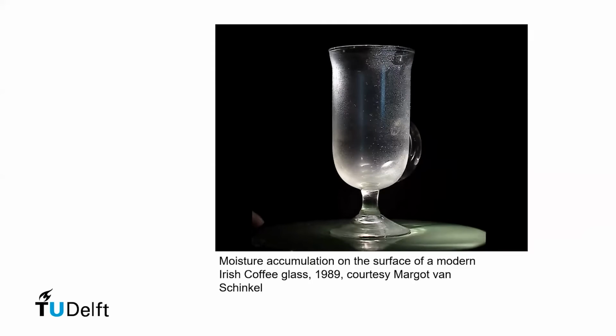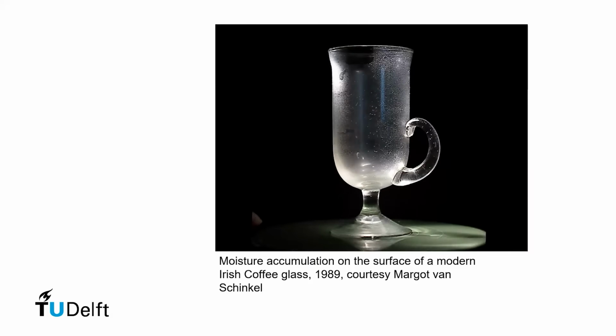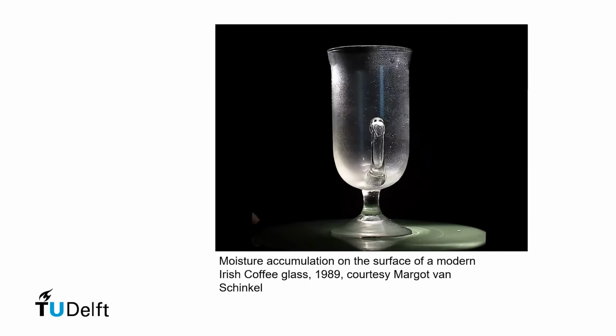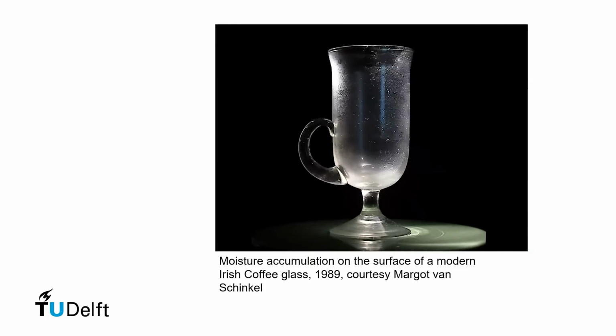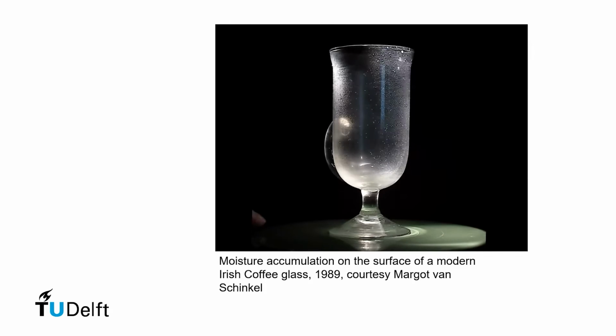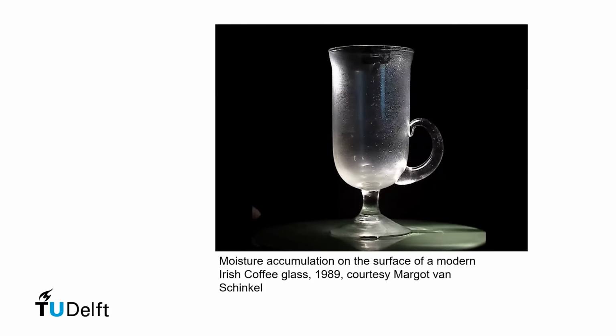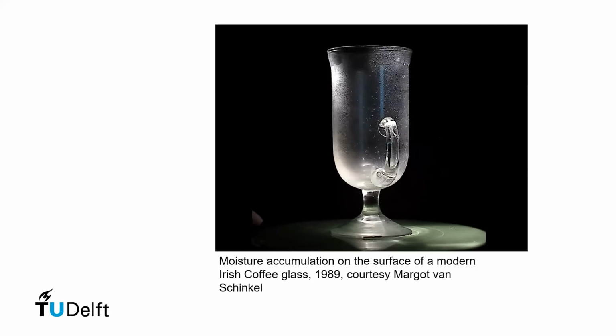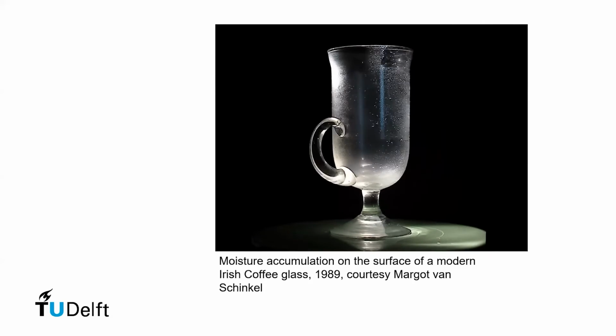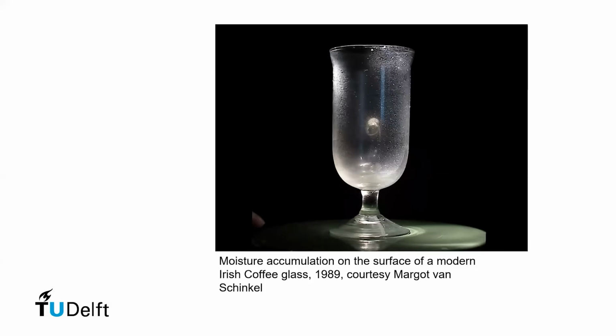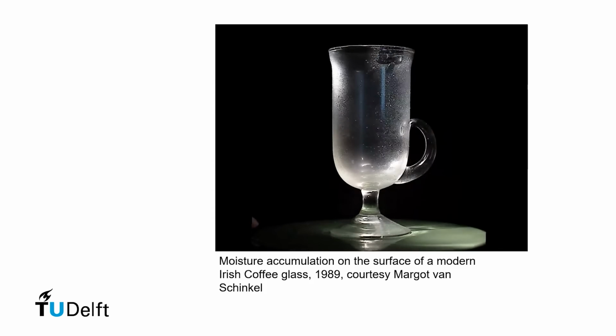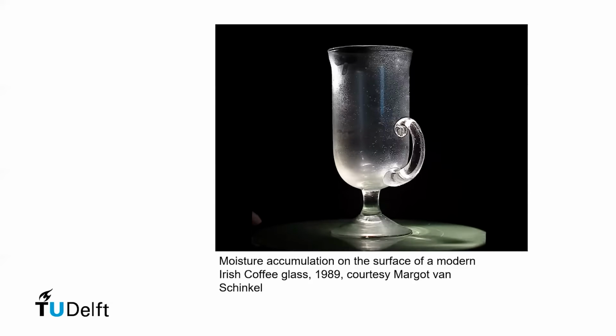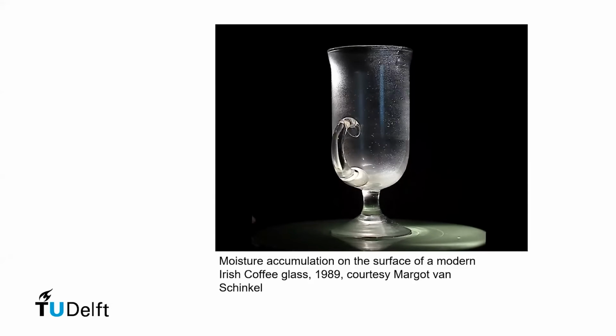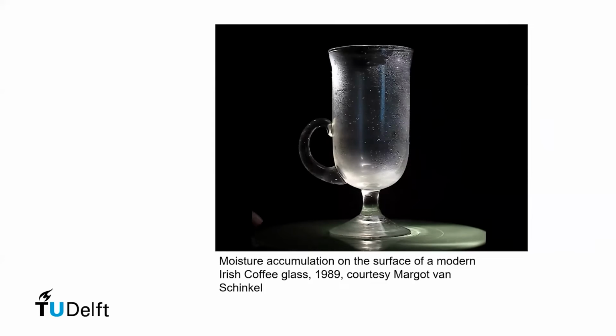And just to show you some examples of what it might look like, this is actually a study object, which was kindly donated to me by a colleague at the Rijksmuseum, Margot van Schinkel, who had this object in her kitchen cabinets, but she didn't use it. It's an Irish coffee glass, but she never used it. And suddenly, when she was cleaning out the kitchen, she found these objects, and what struck her was something that she was very familiar with, namely the accumulation of moisture on the surface of a glass. And this is one of the main degradation patterns we observe in museum collections, that glass that deteriorates accumulates moisture on the surface. And as Astrid mentioned, this is a problem because water is the main culprit for degradation. So that might accelerate the degradation.